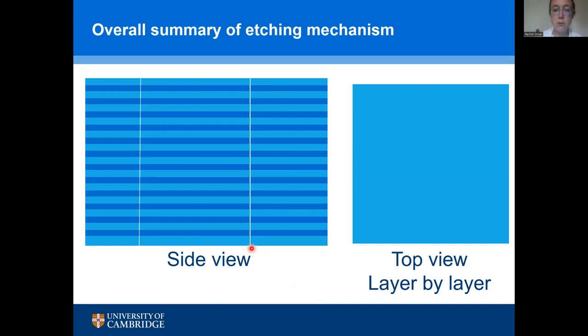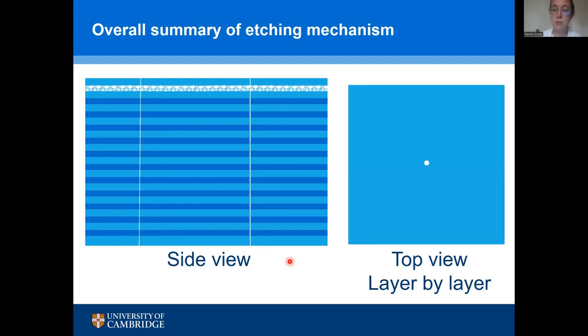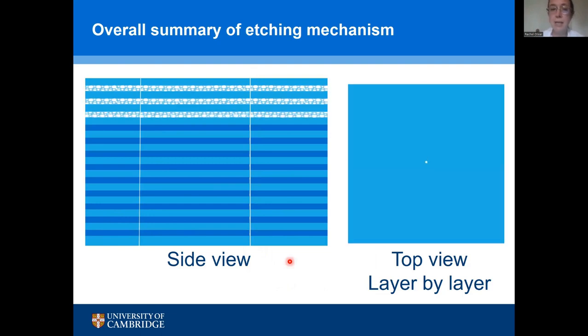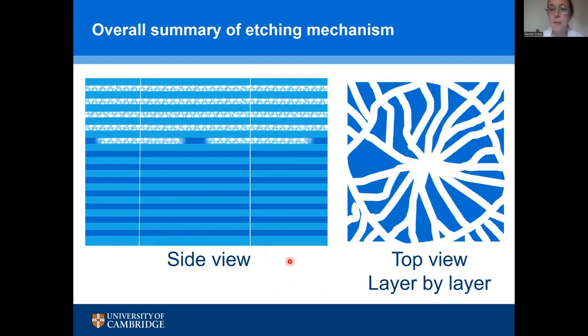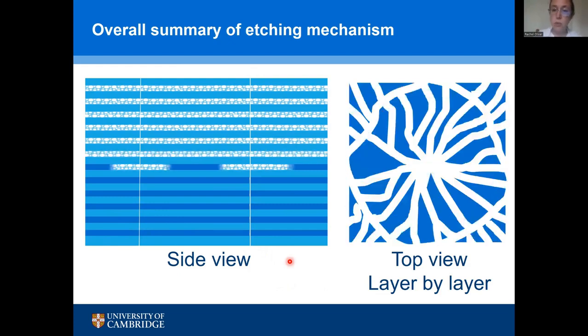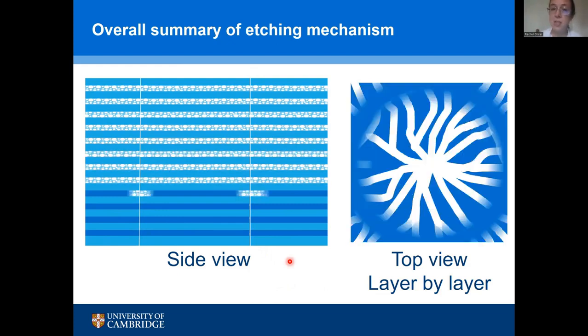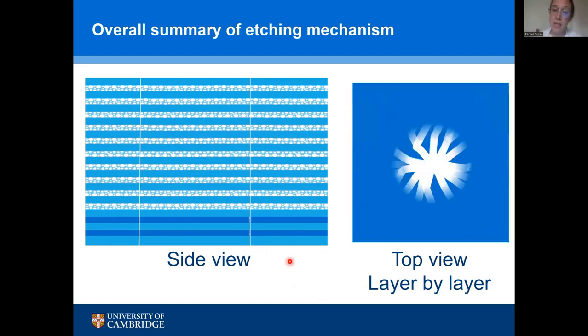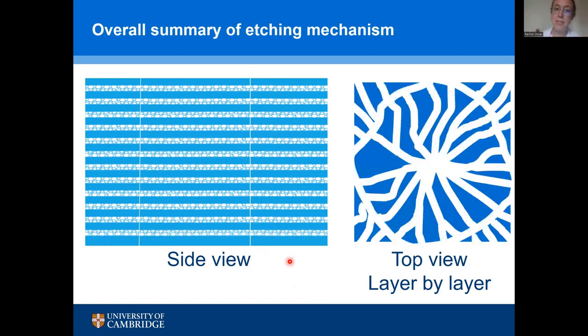So that then allows us to summarize what's going on with the etching mechanism. If we start off with these defects, these dislocations running through this material, which consists of doped and undoped layers, when we turn on the bias, we essentially first open a pipeline at the defect, and then from there the etch heads outwards through the conductive doped layer until that layer's all etched, and then we open the pipeline to the next layer, etch the next layer, and so the etching proceeds through the defect pipeline all the way through the stack.